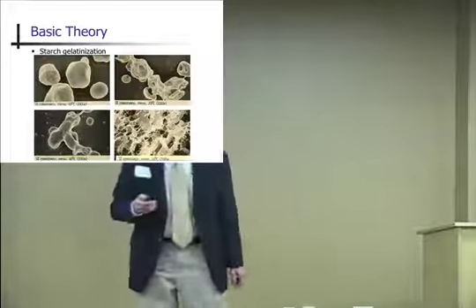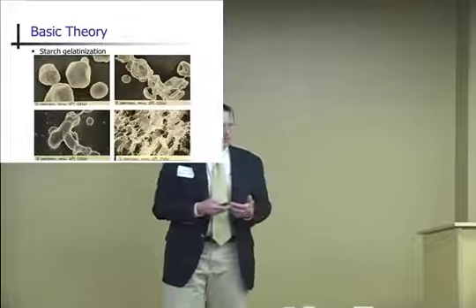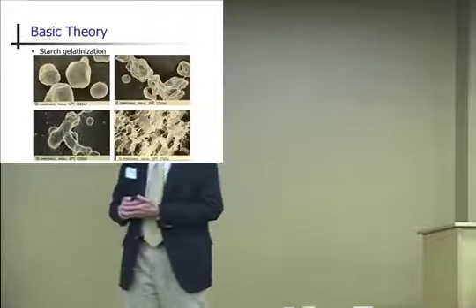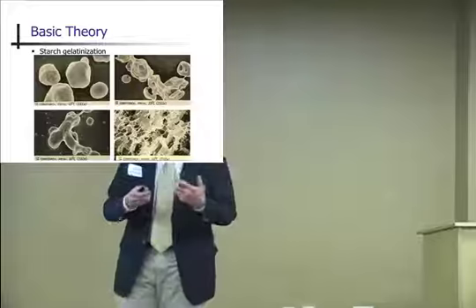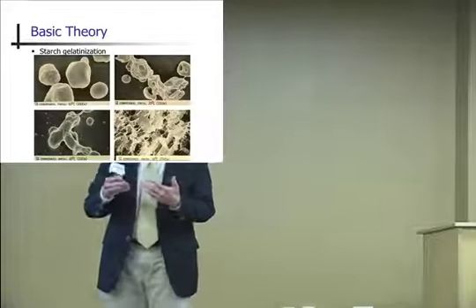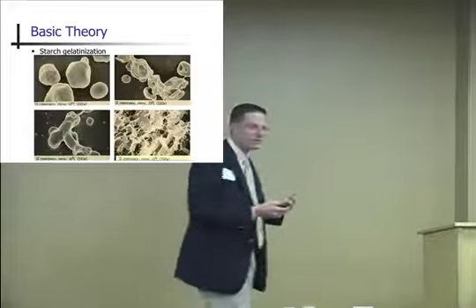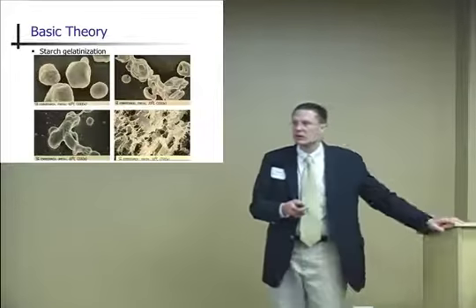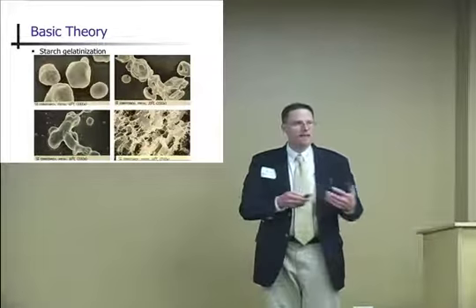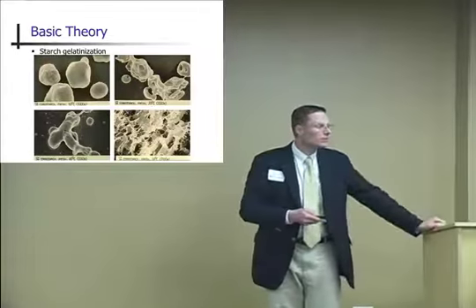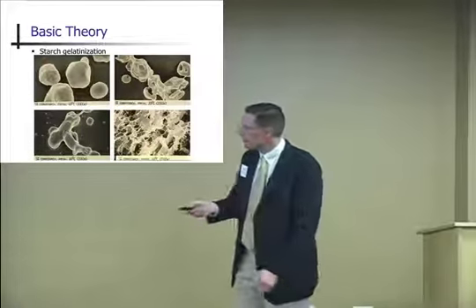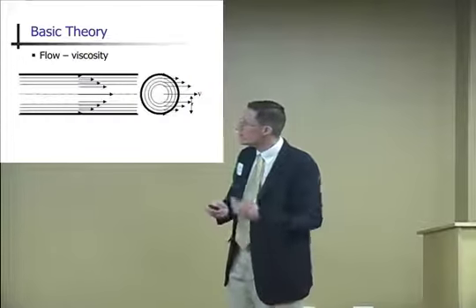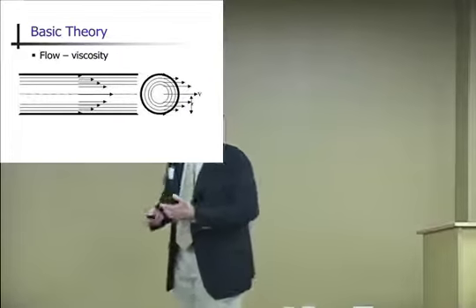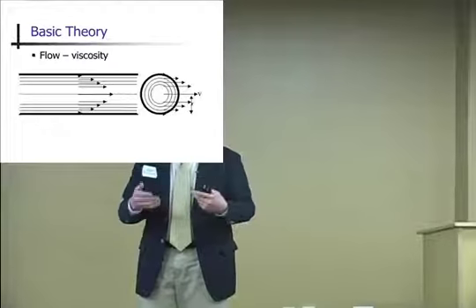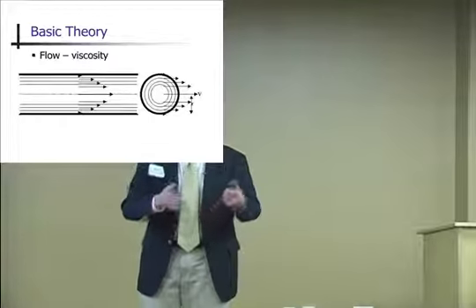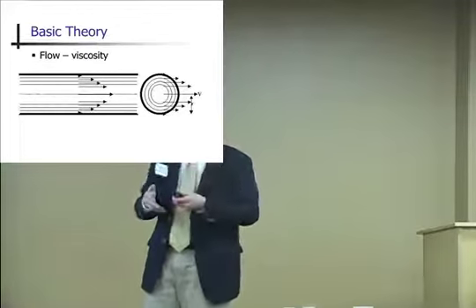So typically, when you're extruding feeds, you need to get above 90 degrees Celsius in order for that starch to gelatinize. And depending on what starch you're working with, whether it's a rice starch or a corn starch or a potato starch or other starch, you may need to get above 100, 110. So what starch does as it melts, and as the other ingredients melt, we need to think about viscosity. Because when those ingredients become liquid, they flow.